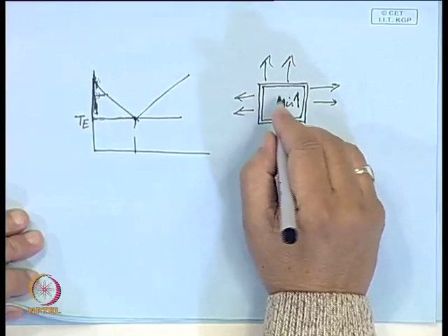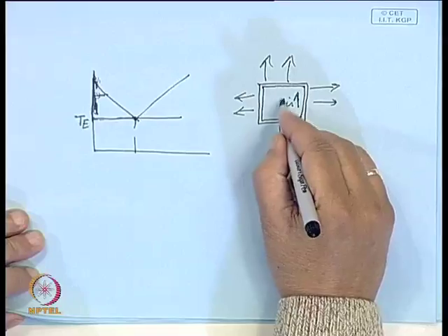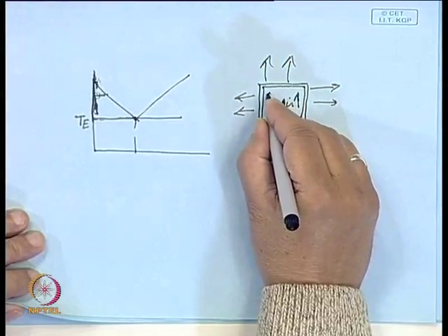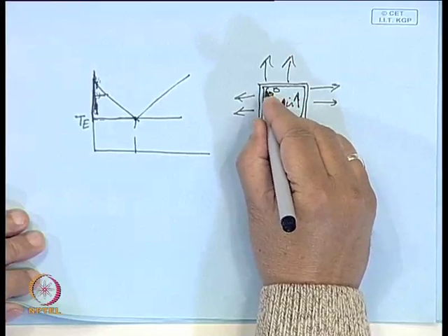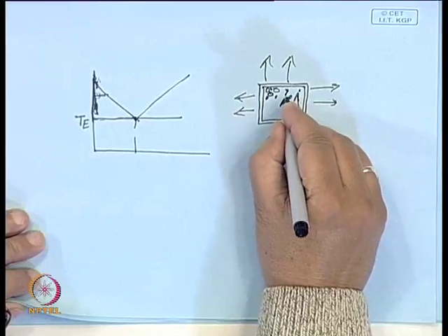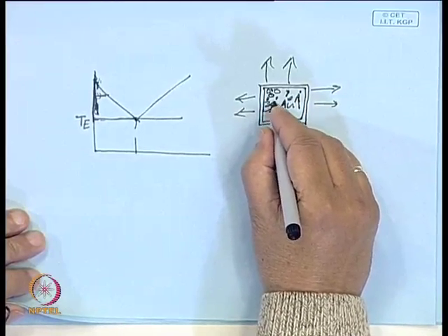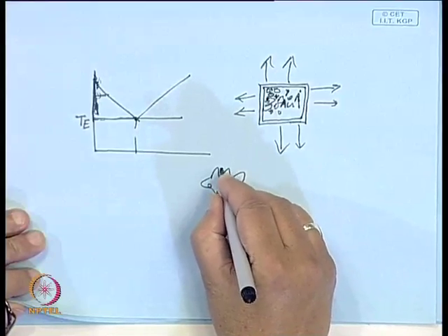ice, because heat will be extracted from the top as well, and the ice is lighter. Therefore, the ice puts a cover, and the air which is trapped is not able to come out. So once these ice crystals form, the air bubbles will also get entrapped between the dendrites of ice, these crystals of ice, and in the channels between the crystals there will be air bubbles, and this is what you see.